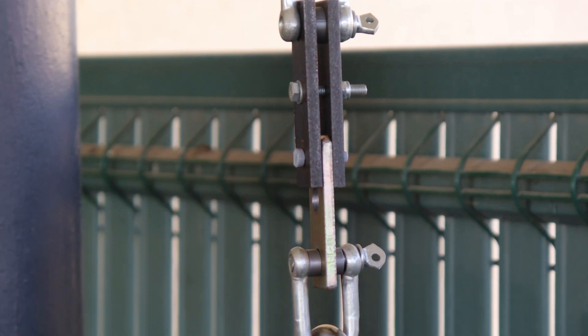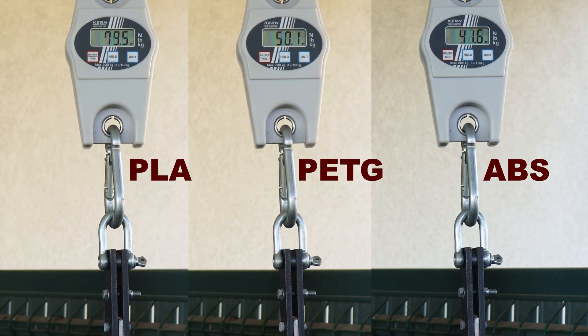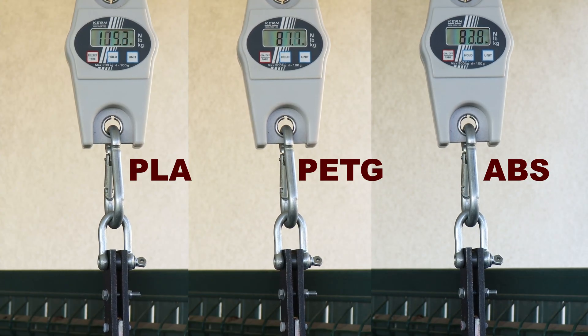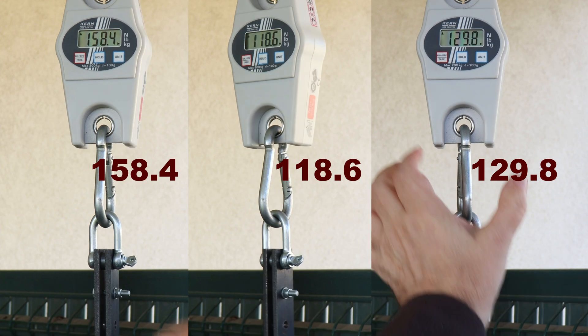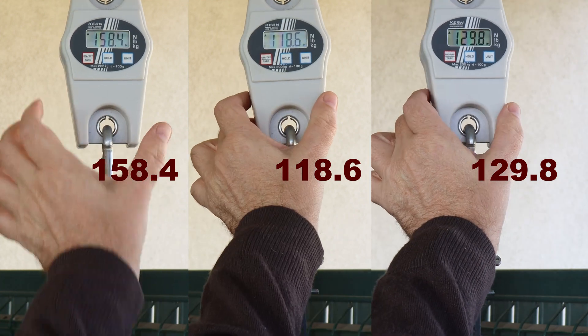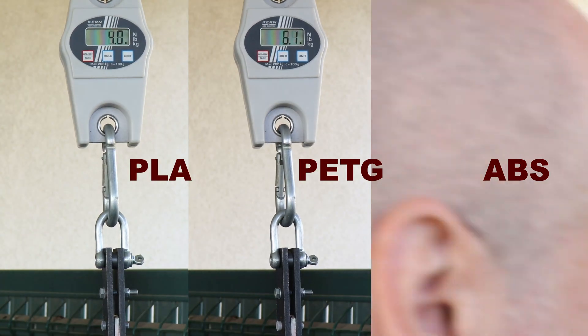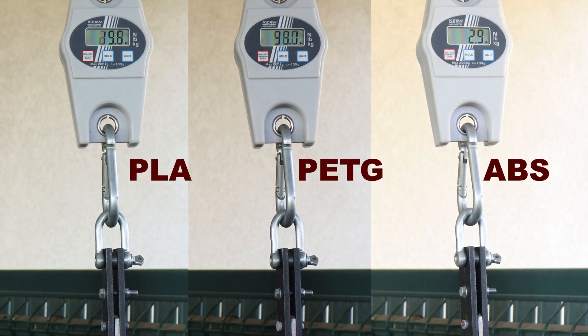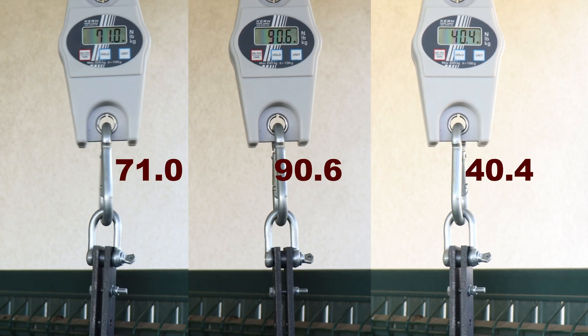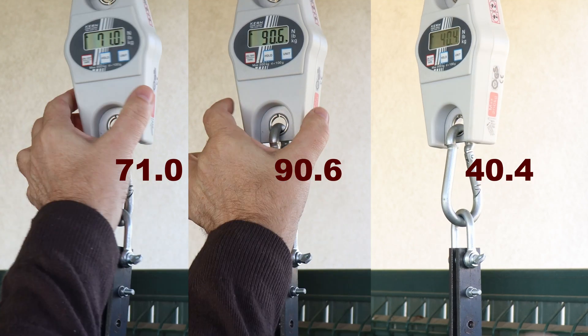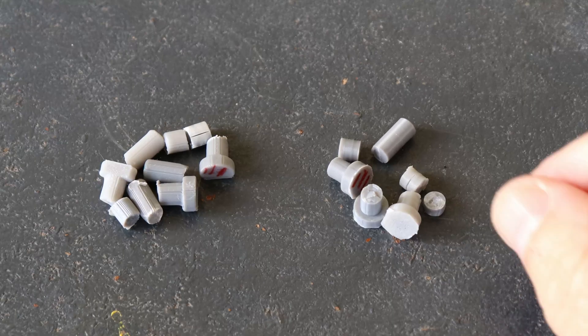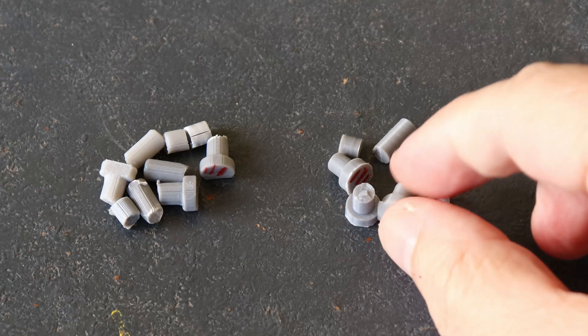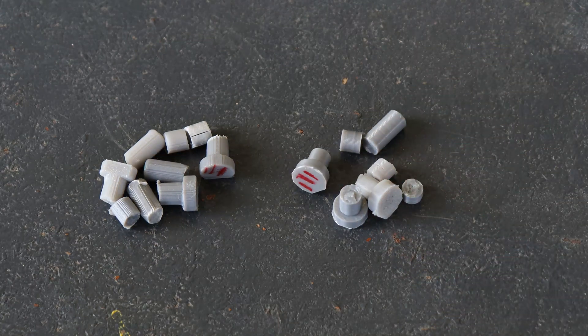Now two-sided shear stress with horizontally printed test objects. Here you can see side by side all three test objects—PLA was the strongest here. Then with vertically printed test objects, of course PETG was the strongest because of the best layer adhesion. All test objects sheared correctly into three pieces.